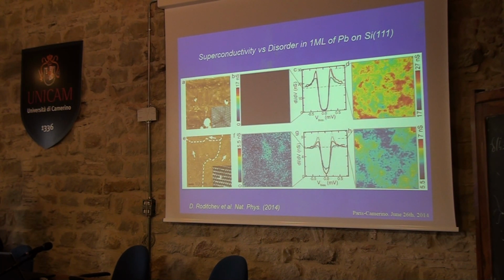And this rise is not really point by point correlated to the disorder, but rather takes into account a total disorder. You see? So in the sense they do not only appear on the grain boundaries, they are spread everywhere. Yes, you have more effect related to grain boundary, but if you look at the topographic image and compare it with the zero bias map on the right image, you don't have a real complete correlation. However, you have it overall. But there is no correlation one by one. It is not a local effect. It is a non-local effect.